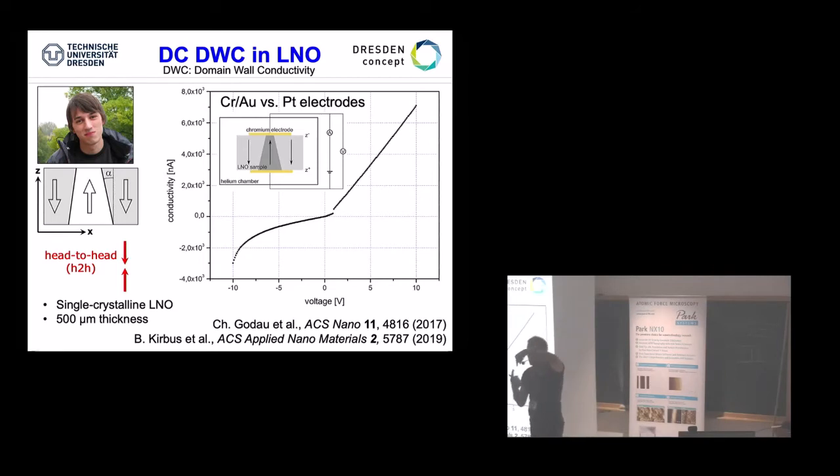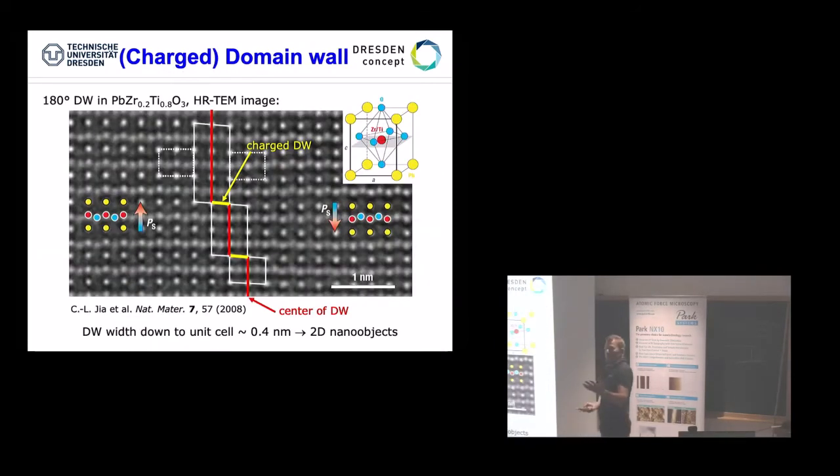So there are really the arrows, and if you digest that, it simply means we're expecting electrons to hop along that domain wall to the other electrode, not the holes, because for holes we would have to engineer a so-called tail-to-tail, T to T. This is H to H, which is head-to-head. So yes, there must be some kind of inclination.